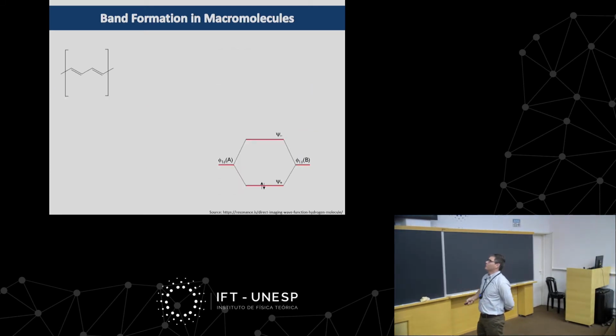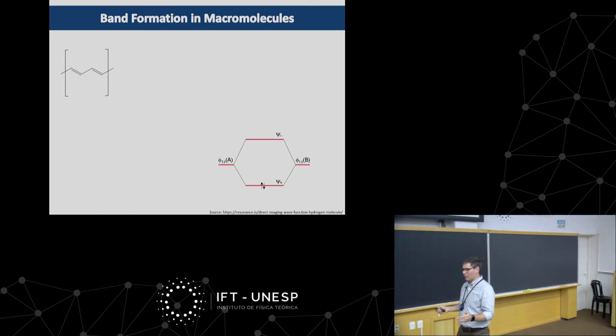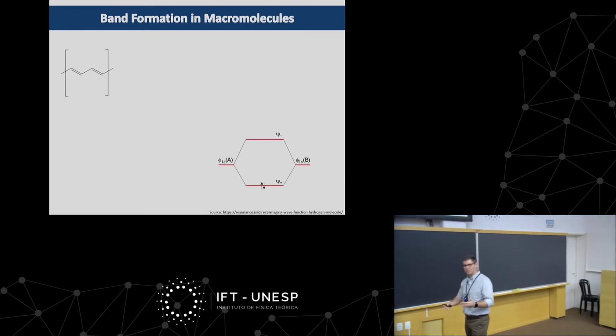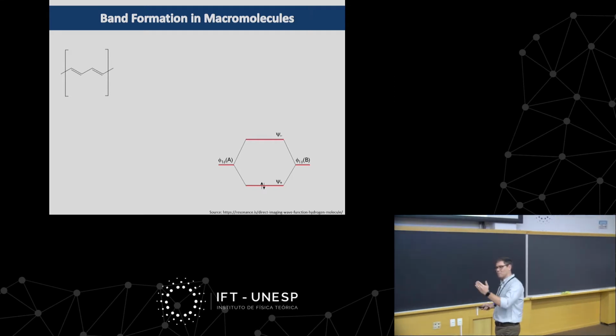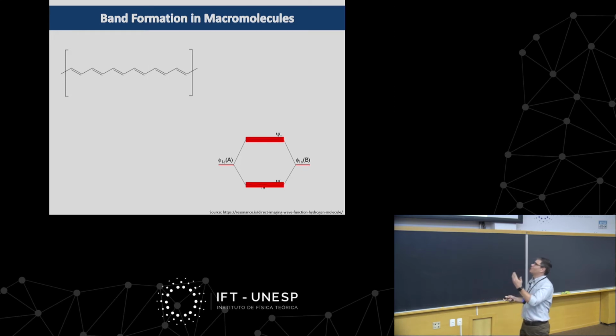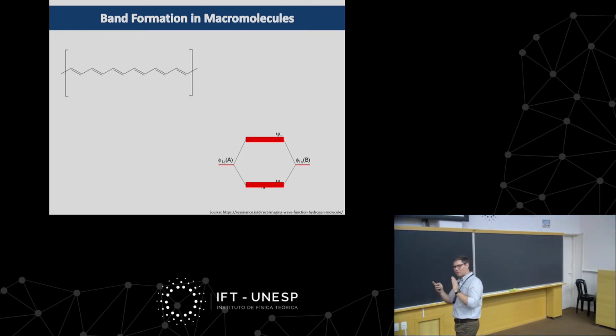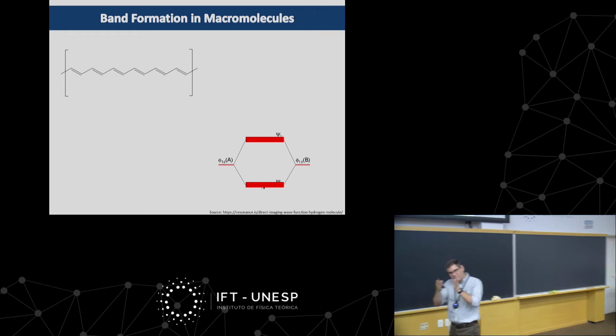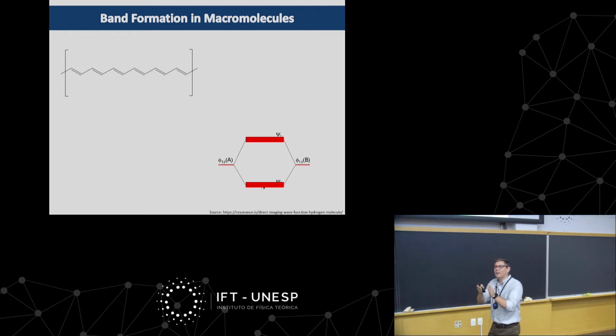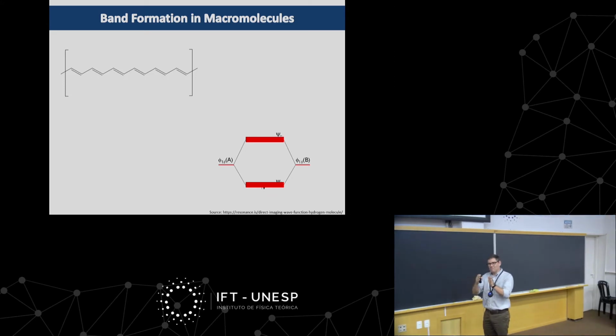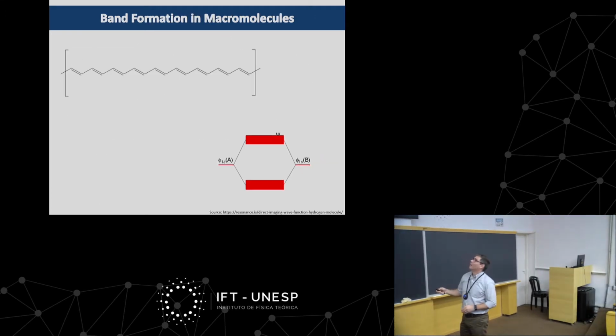But those are discrete states. So if you would have a transition between these 2 states, they are very narrow. But we know that polymers are amorphous materials. Those transitions are far from being very narrow. And actually, we don't call these states, we call these bands. And the way you form a band is because a polymer is a lot of similar monomers, which is basically the same repetition unit that actually repeats several times in order to form a very long chain.